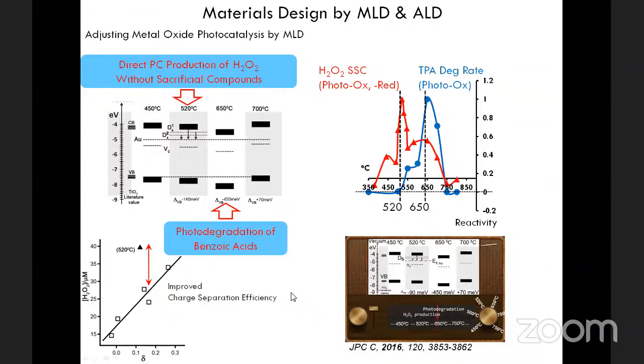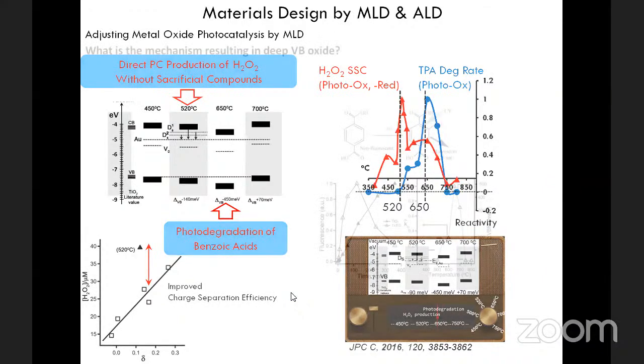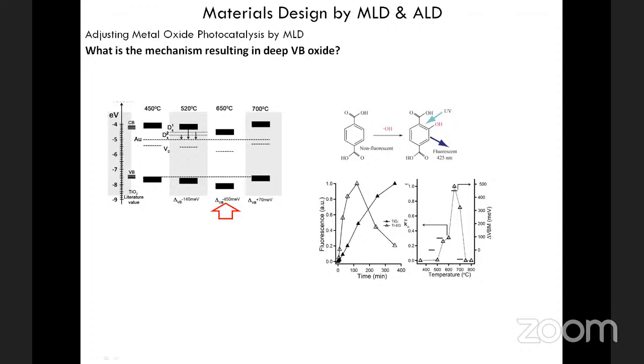So this gave us some nice understanding of the unique features that are obtained by controlling the processing temperature. But we still remain with a bit deeper question. So what is the mechanism resulting in deep valence band oxide? So one cannot explain the deepening of the valence band by defects, because defects usually will destabilize the system, and this will make an upshift. And also doping is not appropriate for this.